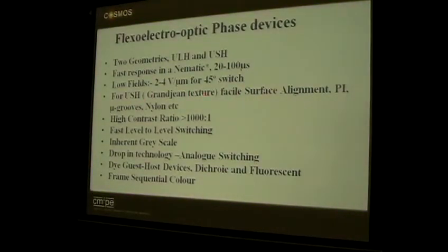I had facile surface alignment. It is incredibly easy to align a chiral nematic. It is the easiest thing to do. You can do it as simply as taking two glass plates, putting your thumb on the glass plate, and pulling it across the surface. The grease that's in your fingers will give you a very thin, almost monolayer alignment. And you know that's how Merck used to test in the early 1980s their cholesteric chiral nematic materials. If they wanted alignment, they just put their thumb on the plate and drew it across the glass. It's very easy. That's all. Okay, so it's very easy to align the USH texture.